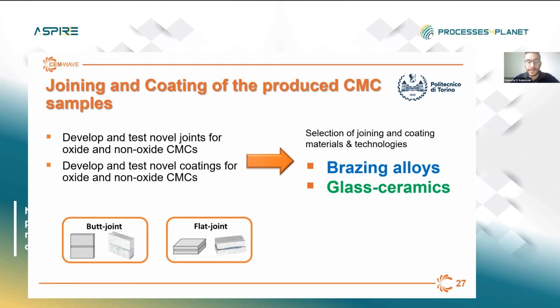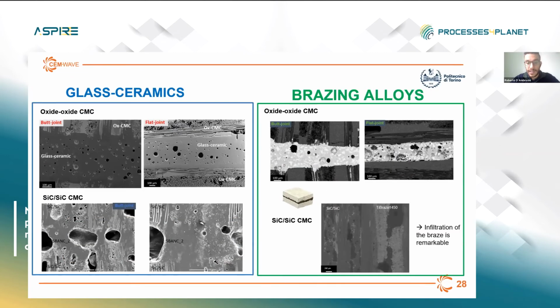So in order to reach these goals, joining materials with suitable compositions have been developed, which were based on brazing alloys and glass ceramics, paying special attention to pressureless joining technologies in order to guarantee the achievement of industry-friendly solutions. As you can see, both these glass ceramics and brazing alloys compositions have been optimized, selecting them in order to guarantee higher temperature softening points based on the operating conditions expected, but also a high wettability and comparable coefficient of thermal expansion. As you can see from the comparison of the failure surfaces, a very good adhesion was obtained for both solutions applied, which have been tested on actual CMC substrates, so both oxide and non-oxide based materials.